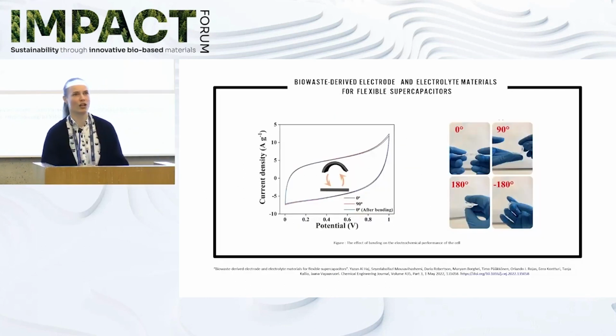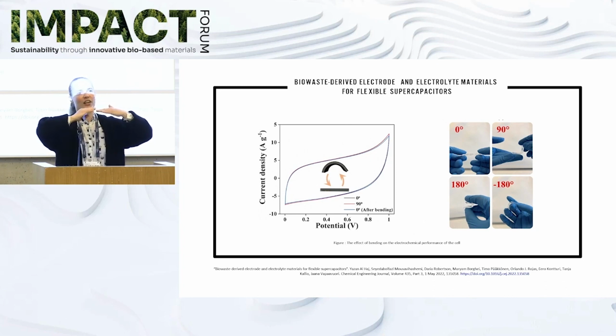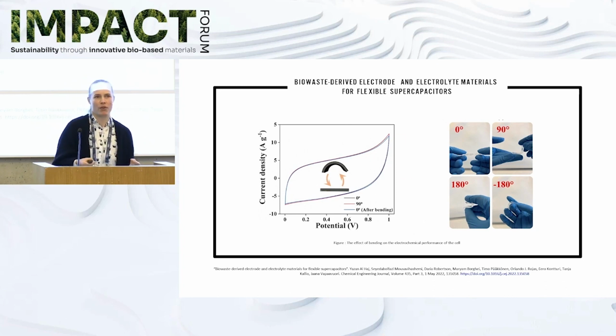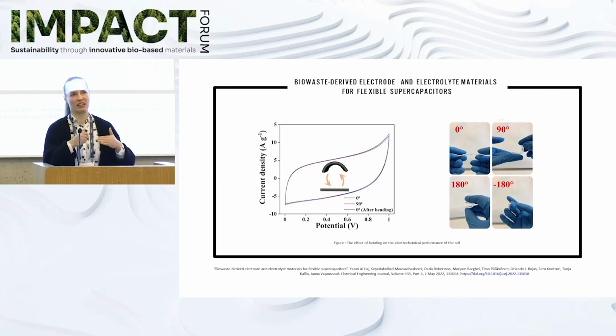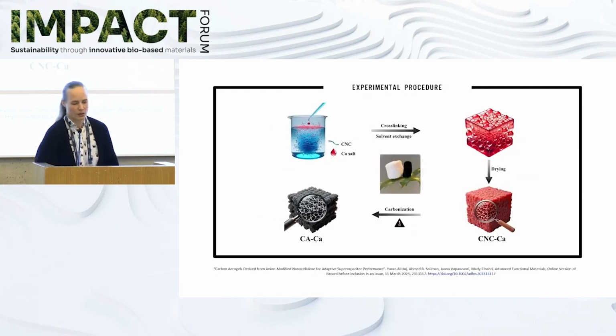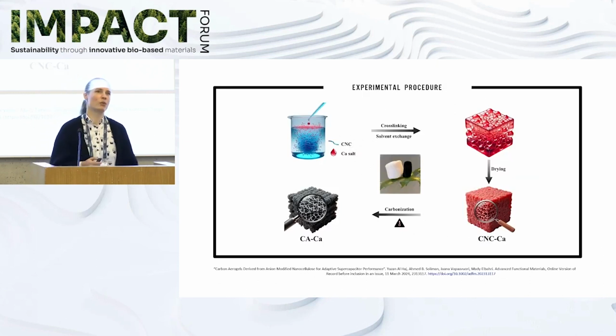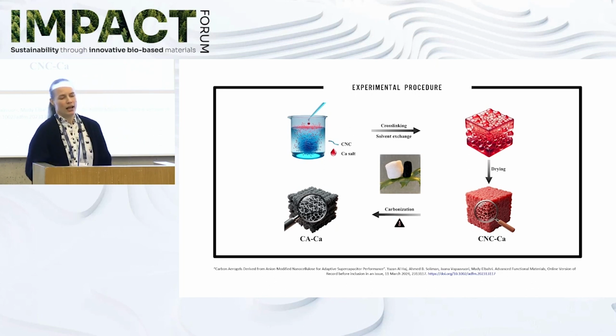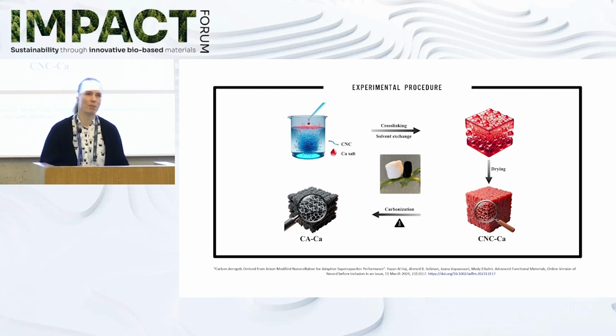And now when you look at the functional properties of these sandwiches, what was really nice is that they are highly bendable, so you can go down to 90 degrees and back, and as you can see in this figure, the performance of these devices is pretty much unaffected by this bending. And here in the other figure, you can also see that it's quite easy to handle these nanocellulose electrolytes. Now, this is a bit more recent work from this year. So we've now been optimizing more of the electrode materials, again, by using cellulose nanocrystal ionically cross-linked gels. And here in this paper, we showcase that we have a very fine control over the porous carbon electrode structure.